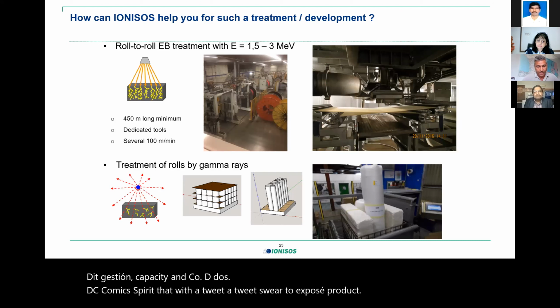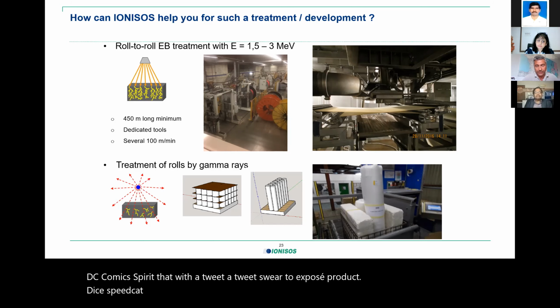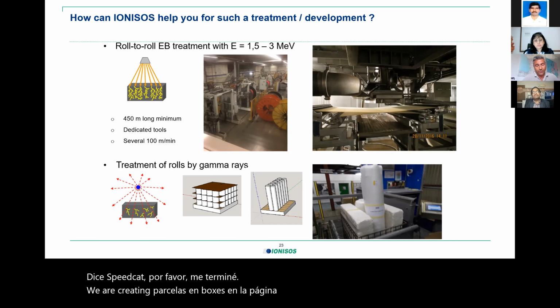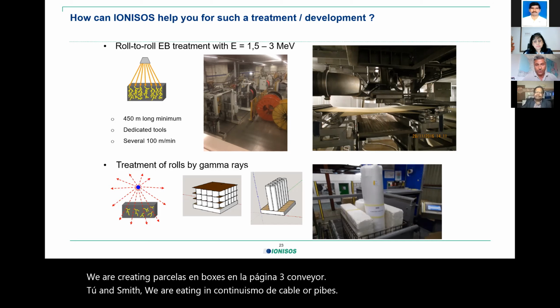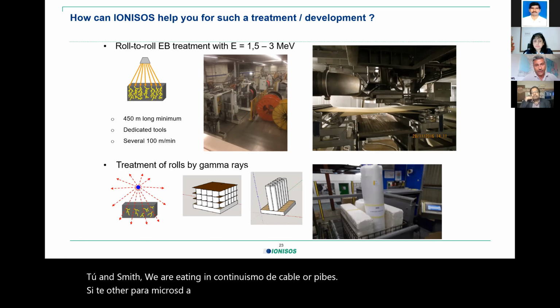This speed can go, for example, from meters per minute when we are treating parcels and boxes in a tray conveyor, to hundreds of meters per minute when we are treating in continuous mode cables or pipes. The other important parameter is the scan width. We need to adapt the scan width of the beam to the width of the product, the width of the tray, or the number of passes of the cable under the beam.